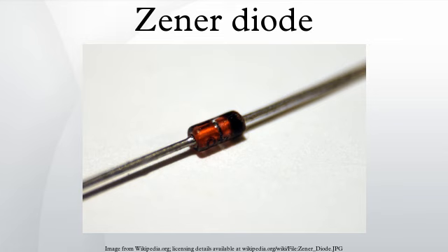In this approach, the base doping profile usually narrows towards the surface, creating a region with intensified electric field where the avalanche breakdown occurs. The hot carriers produced by acceleration in the intense field sometimes shoot into the oxide layer above the junction and become trapped there. The accumulation of the trapped charges can then cause Zener walkout, a corresponding change of the Zener voltage of the junction. The same effect can be achieved by radiation damage.